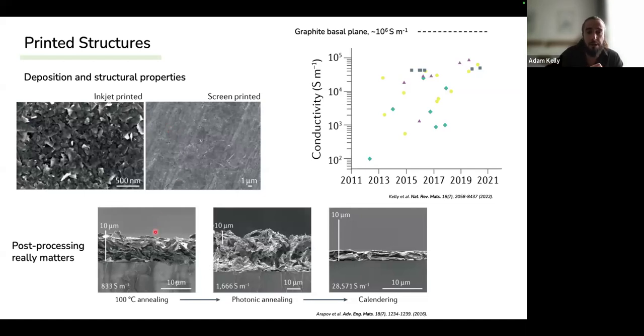So this is a screen printed network of graphene. And this is done by Arapov et al. And what they found is a conductivity of their network of about 800 Siemens per meter. That was after 100 degrees annealing in the screen printed network. They applied photonic annealing, which actually, because of the volatilization of the polymers that were in there, the network got much thicker, but the conductivity still increased, which is very, very interesting. They then compressed the network to annihilate all of the pores and porosity. So it became much, much thinner. And this had the consequence of increasing the network conductivity by about an order of magnitude.